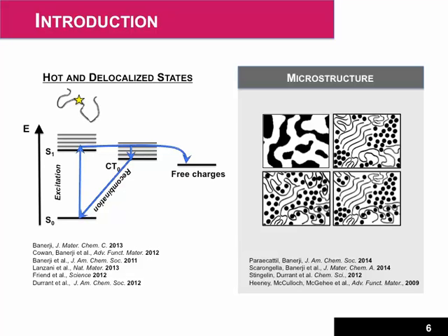And then, as I said, there's this question of microstructure, which is the one I'll be talking about most today, because you don't really get this black and white picture. You can have the polymer and the fullerene completely separated, but then your polymer can form all sorts of crystalline or amorphous phases, and depending on how the packing is, it can give a very rich energetic landscape. But most of the time, the fullerenes can really intermix with the polymer.